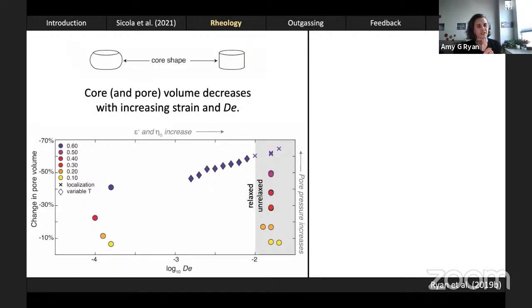I would also sort of imagine that it would become a runaway effect a little bit, particularly at high strain, if I'm getting really significant pore volume reduction and thus increased pore pressures, you'd imagine that any sort of perturbation of the system, some small drop in pore pressure from two bubbles linking up, would have the runaway effect of essentially making a fracture propagate outwards. And maybe that's actually how my fractures are starting and propagating, is from one bubble wall failing and then everyone around it sort of responding in kind. But in the viscous flow, I don't necessarily think that that's happening.